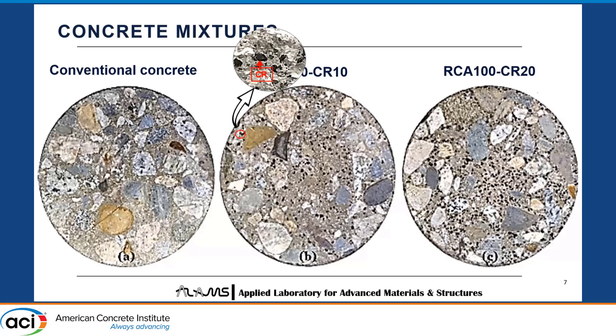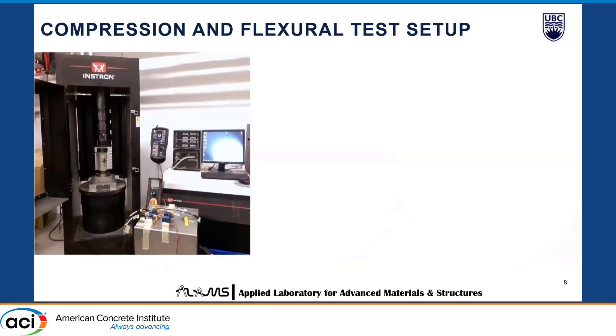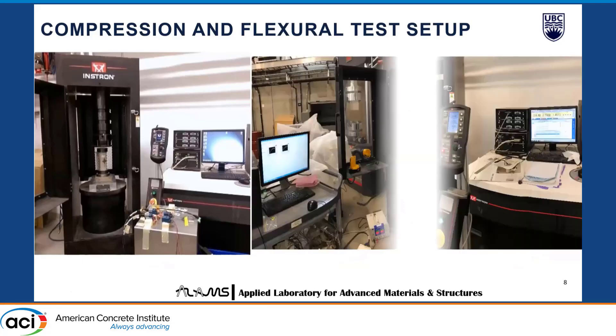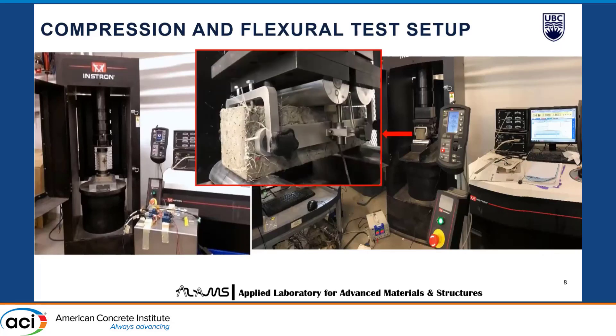As you can see, that's a close-up picture of the crumb rubber in my concrete specimen, and that's a close-up picture of the RCA in my concrete specimen. For the compression test setup, I had standard 100 by 200 millimeter concrete cylinders with strain gauges attached to get accurate stress-strain curves under compression. For the flexural test setup, I had standard 100 by 100 millimeter cross-section and 350 millimeter length beams, testing three beams per mixture. A yoke was built and an LVDT was placed at mid-span so that deflection values could be obtained irrespective of support settlements on both sides.